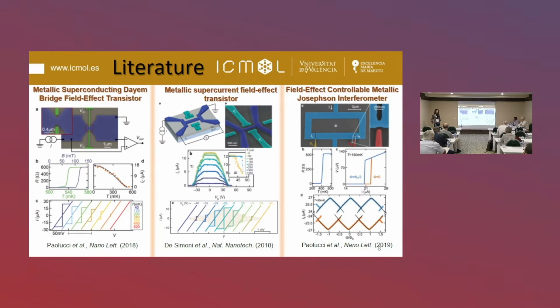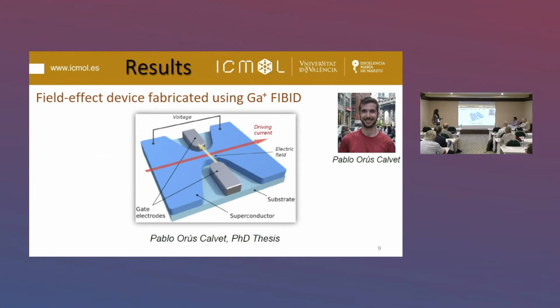However, the mechanism behind this field effect is still very controversial. In order to shed some light on this physical mechanism, and to see if this effect extends to other superconducting materials which are not purely metals, we created such a field effect device using our tungsten carbide material grown using focused ion beam induced deposition, using Ga+ FIB and also using the helium beam.